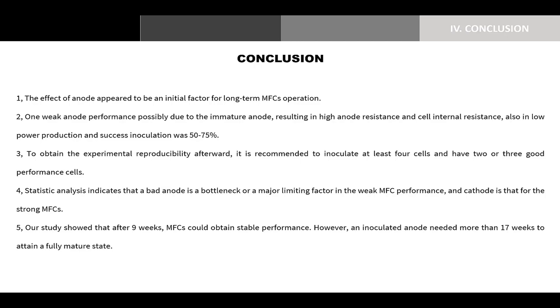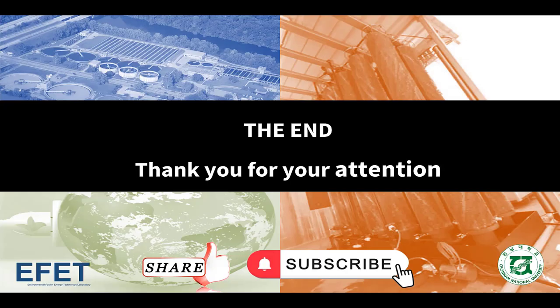Simple linear regression analysis indicated that in the weak MFC, anode was the only statistically significant explanatory variable, and multiple linear regression showed that anode was the factor negatively controlling power responses. Our study showed that after nine weeks, MFCs could obtain stable performance. However, an inoculated anode needed more than 17 weeks to attain a fully mature state.